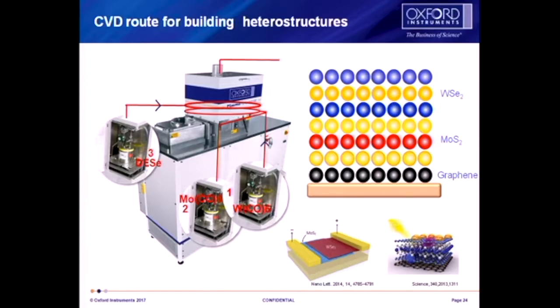You could start building up a complete device, some graphene, molybdenum disulfide, then tungsten selenide on top. Now, selenides cause a bit of a problem because the selenium compounds are very, very toxic. So we have to work out how we can get them on site to do this work. So if anybody wants to partner with us to do that, we'd be very, very interested.